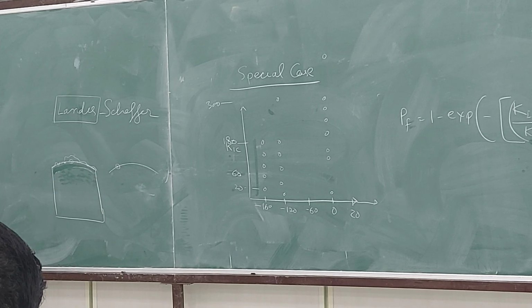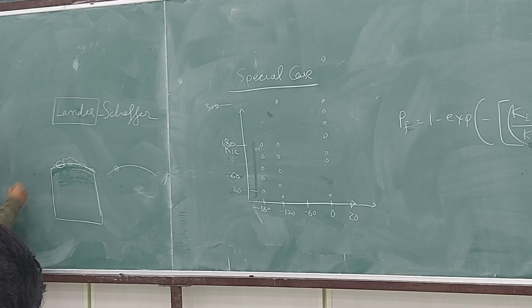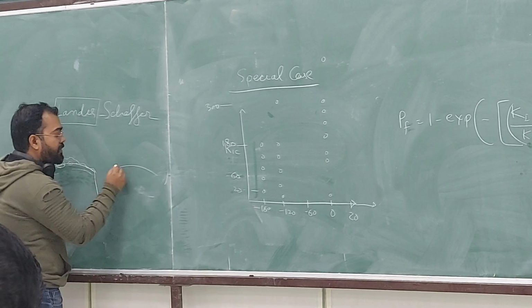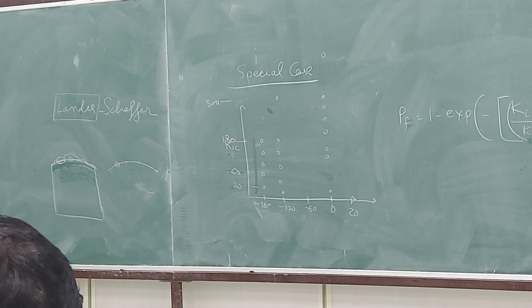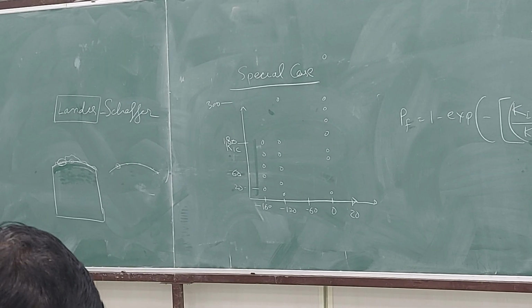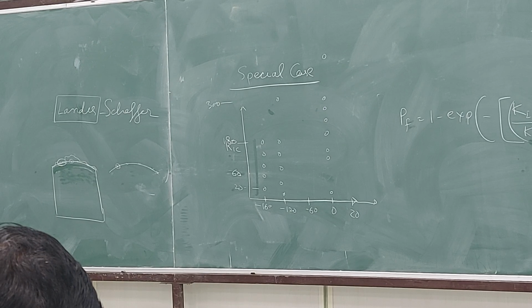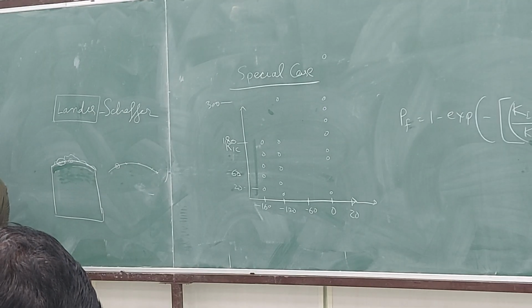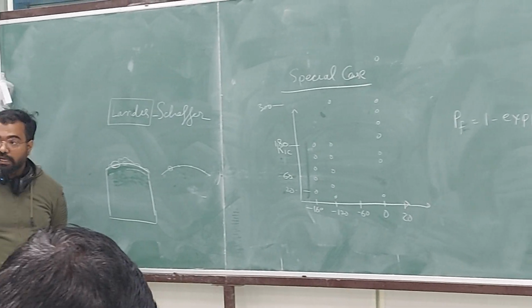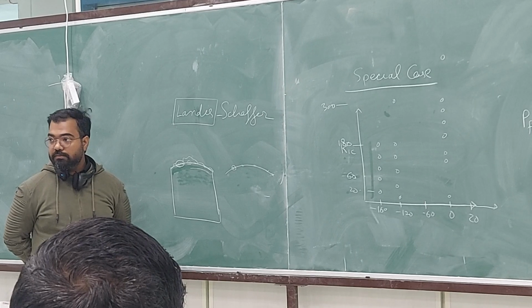The local stress increment by a cluster of 5 particles will be more in comparison to 5 distributed particles. This contributes to the probability. I will have n number of samples, and not all of the samples will have the same amount of carbide distribution at the front. And nobody can control it.